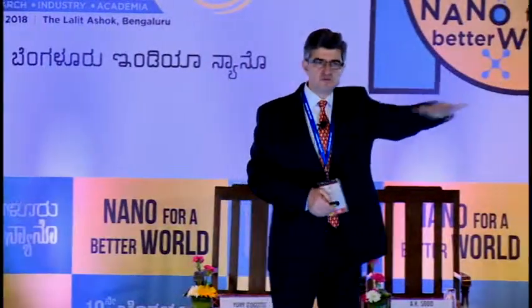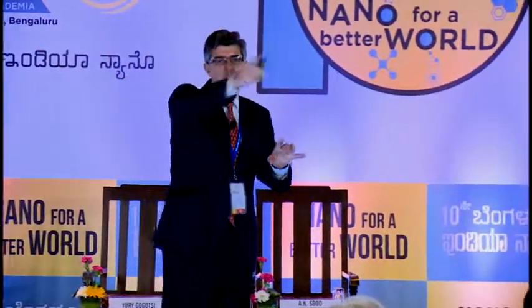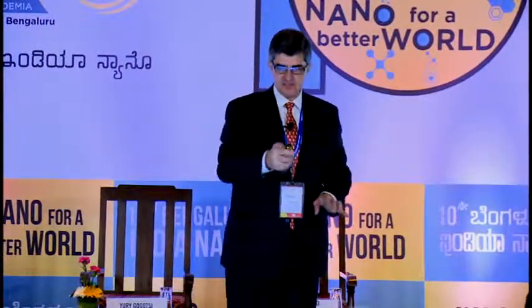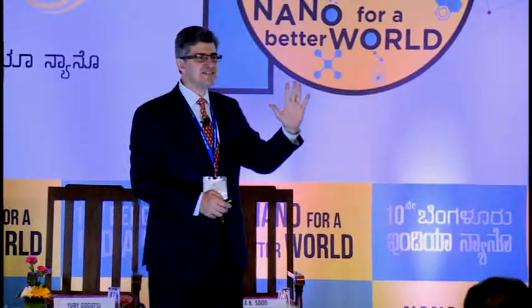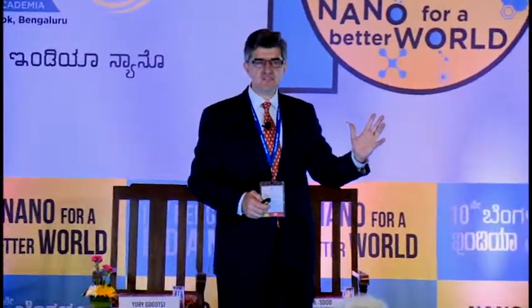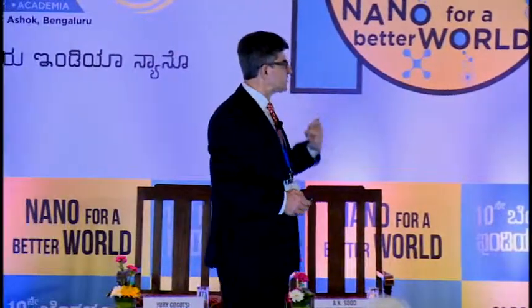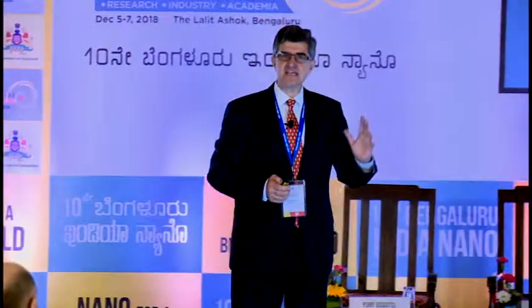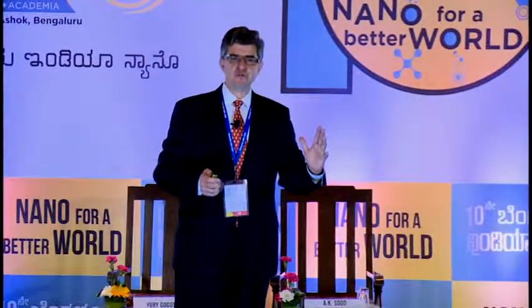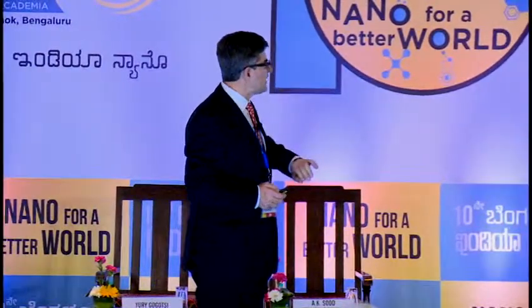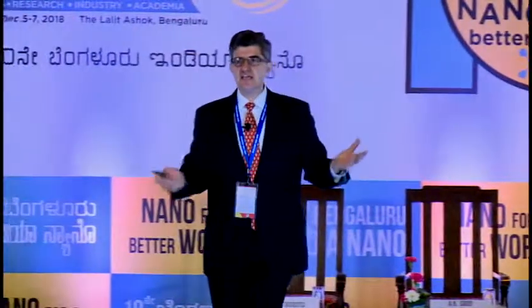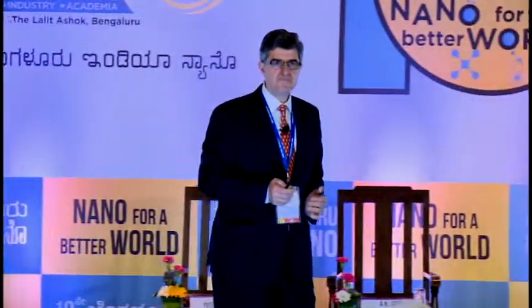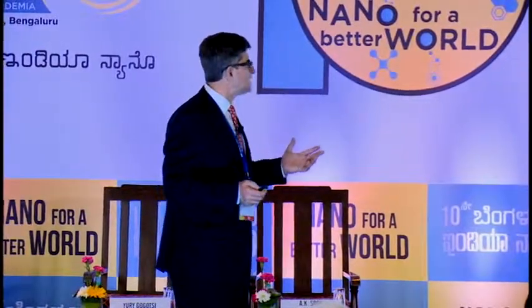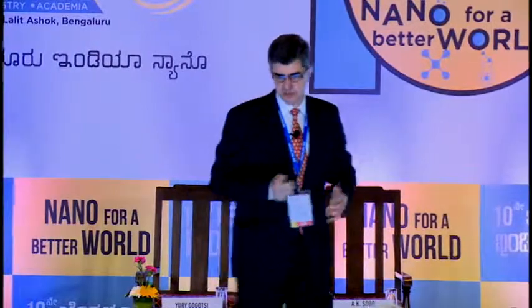When we align flakes parallel to the surface, we can make a thin device because ions have to move around flakes to get through the entire device. If we want to make a thick electrode, we need to make flakes standing vertically here. And again, it's possible. In this paper, we actually used liquid crystal to align the flakes, but now we have shown that with the right flake size and concentration of MXene flakes, the suspension has liquid crystalline behavior, so we can align them vertically. As a result, whether we have, for example, a 40 micron or 200 micron film, it gets pretty much the same capacity. So it becomes not diffusion limited in the direction normal to the electrode surface here. So all these applications open up when we learn how to control and design structures with these two-dimensional flakes here.